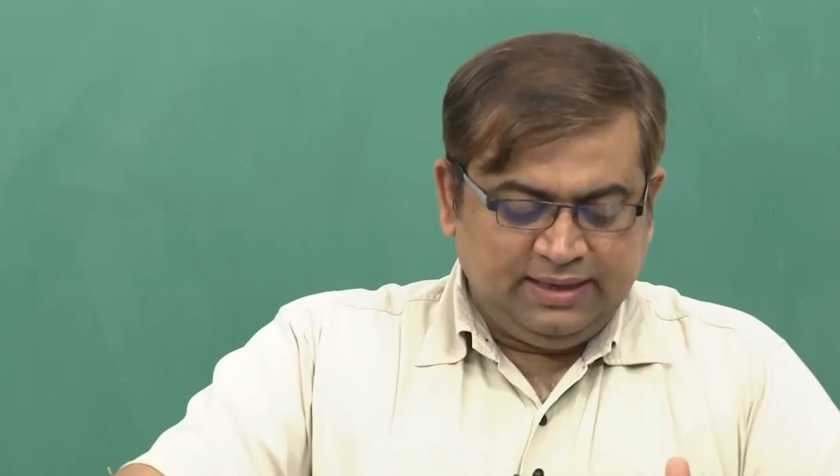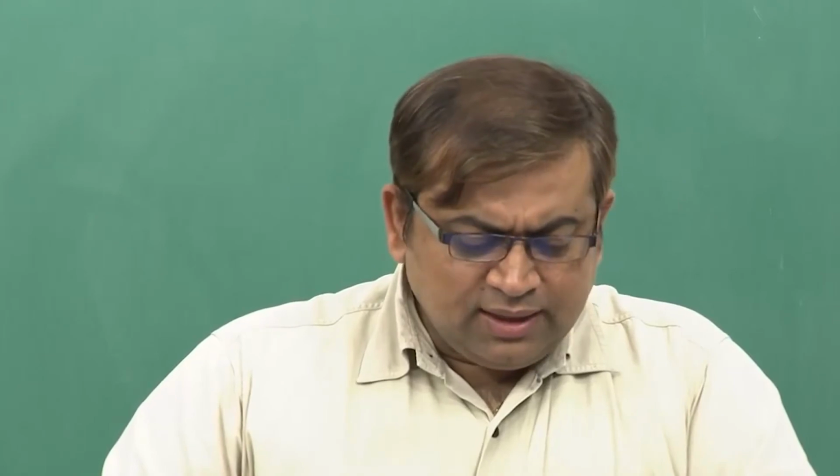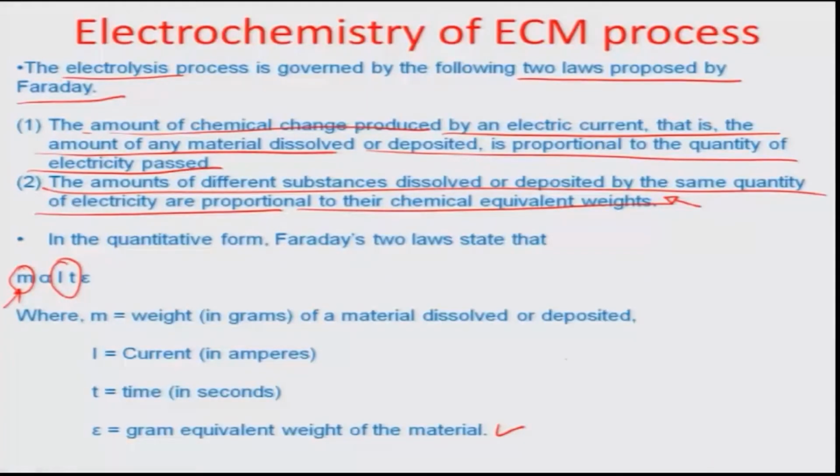Okay, and so therefore the quantity of charge that is involved there is obviously going to define how much mass is going into the solution. So the other important issue here is the gram equivalent weight of the material. So the gram equivalent weight of this material is basically the atomic weight divided by the valency